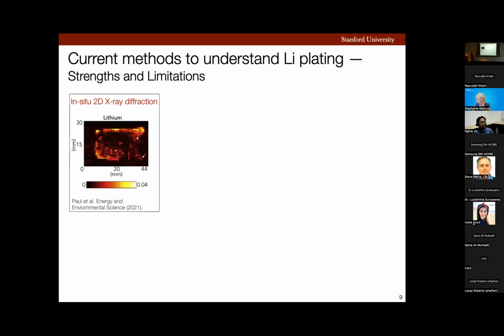First study was led by SLAC scientists, in which they employed in situ X-ray diffraction to create 2-dimensional mapping of plated lithium in these industry-relevant pouch cells. Their data demonstrated the spatial heterogeneities of lithium plating span in X and Y direction, so laterally. But as you can see, this study was limited to 2D, and translating it to 3 dimensions is very difficult. In addition, this study was limited to millimeter scale resolution.